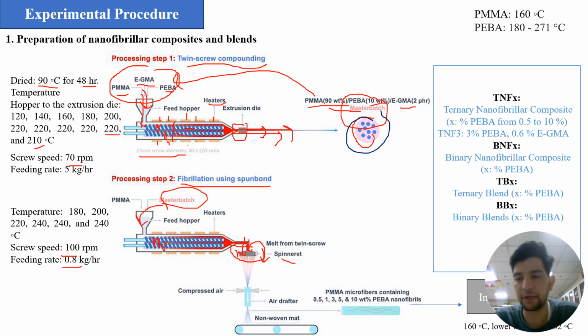The stretching of the filament results in the formation of PMMA microfibers about 30 micrometers in diameter, and the transformation of dispersed PEBA in EGMA spherical particles into nanofibers. So here they show that the filament which is made, we collect in the non-woven mat. In this portion it will stretch and the spherical part will convert to nanofibers. So the author made many samples which contain PEBA at different concentrations: 0.5, 1, 3, 5 and 10 weight% of PEBA nanofibers.